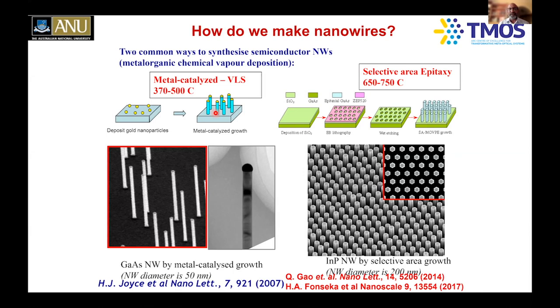Here is an example of 50 nanometer gallium arsenide nanowires grown by my former student, Dr. Hannah Joyce, when she was doing her PhD at the ANU. Now she's an associate professor at Cambridge University, where she has demonstrated excellent performance gallium arsenide nanowires, and also atomically perfect nanowires. The diameter of the nanowire is essentially determined by the diameter of the nanoparticle you choose. We made nanowires as small as 10 nanometers, as big as 300 nanometers, and depending on the application, you choose the diameter you want to make.